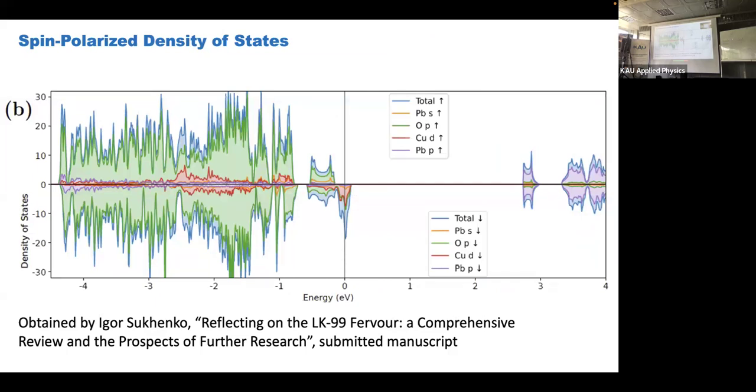Yes, it is still under revision. Also, it was actually put there in this context to demonstrate the limitation of the DFT plus U approach in this case, because experimentally all the subsequent synthesis and synthesized materials prove to be semiconducting. And actually, there is a gap at the Fermi level. There should be one.